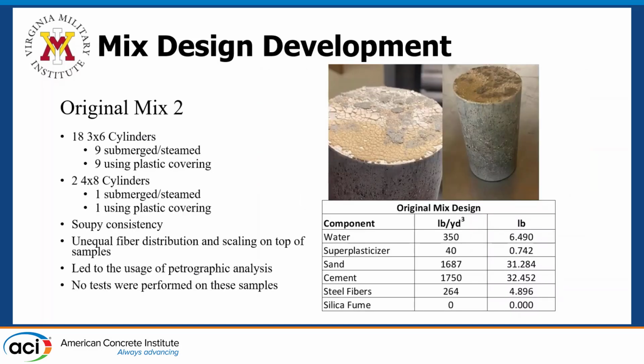Here's our next mix. This one actually presents an interesting problem when you don't dry your sand. So we ended up accidentally using wet sand and we decided to see where it goes. When you're making UHPC, you're working with so many materials that are based on the density of the paste itself. The steel itself actually ended up sinking down into each sample. And that's actually what inspired our petrographic analysis. But there was an unequal fiber distribution, as you can see, scaling on top of each sample. No tests were performed. We figured that any sort of compressive strength we got would be inadequate for the type of research we were conducting.